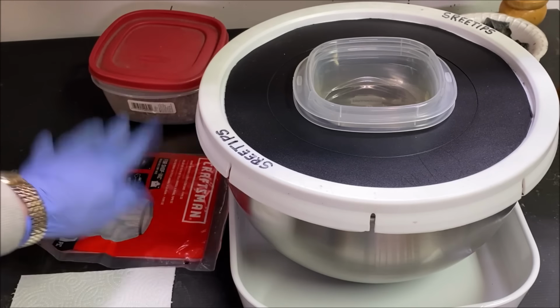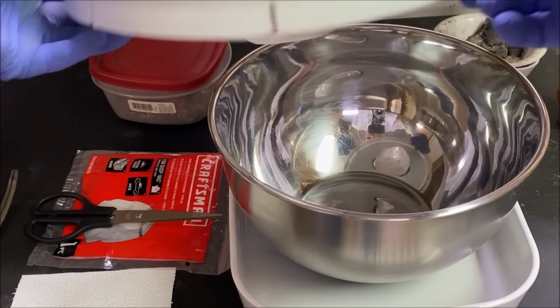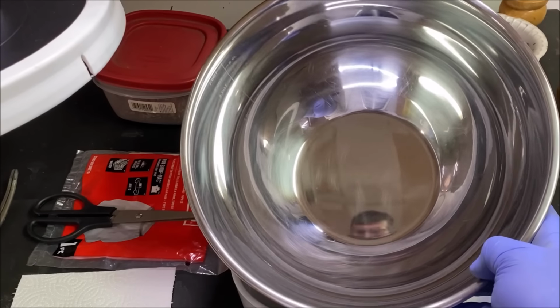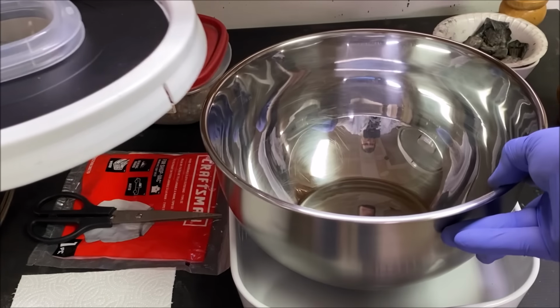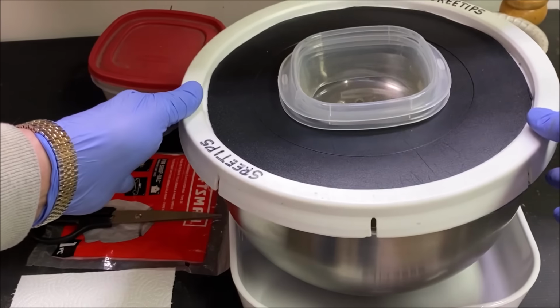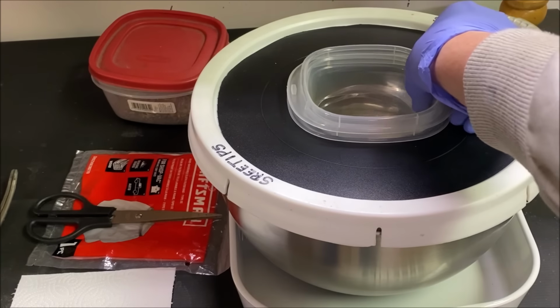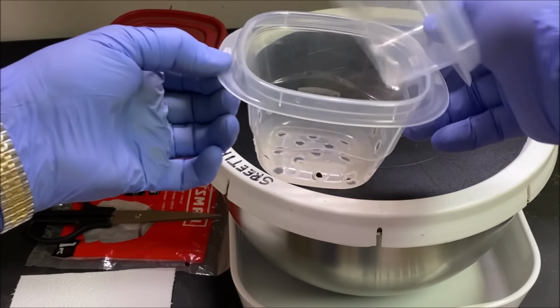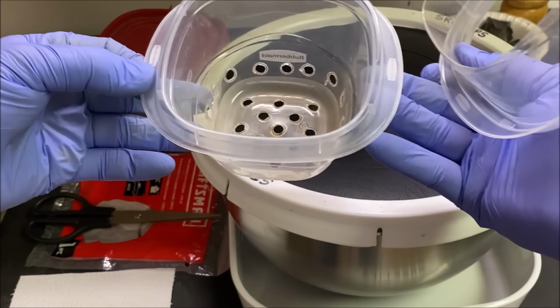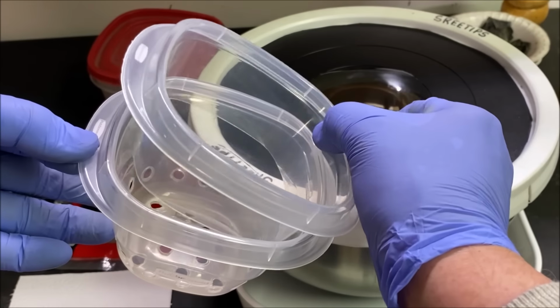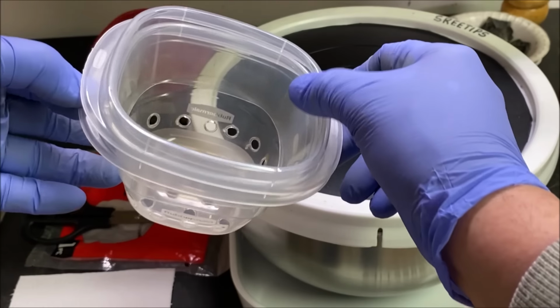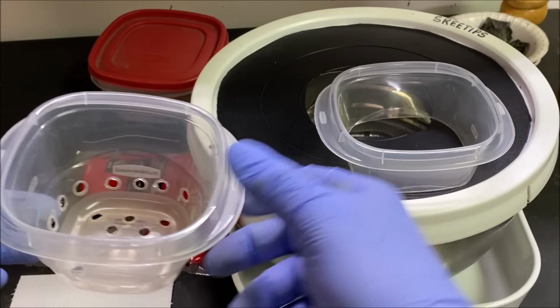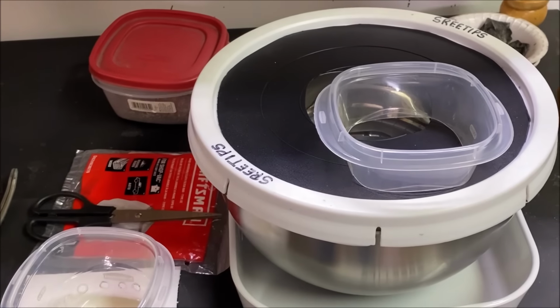Here's the silver cell that we're going to be using. This is our 6-liter silver cell, big one. This thing should crank out about 10 troy ounces of pure silver per day. Here's our anode basket, and then I've got a little spacer on top of here to support the impure silver that we add into this thing.